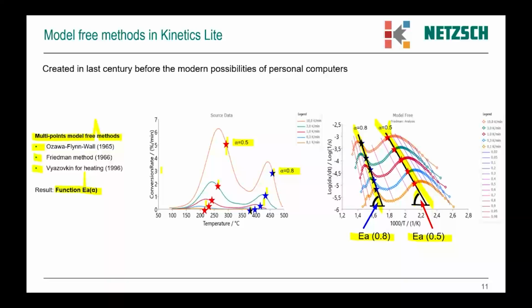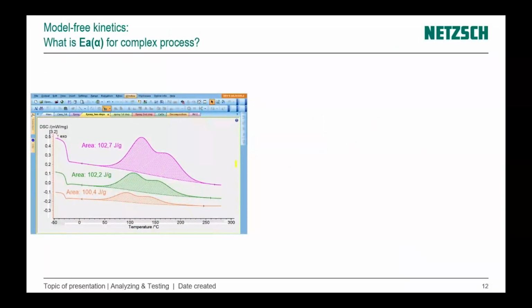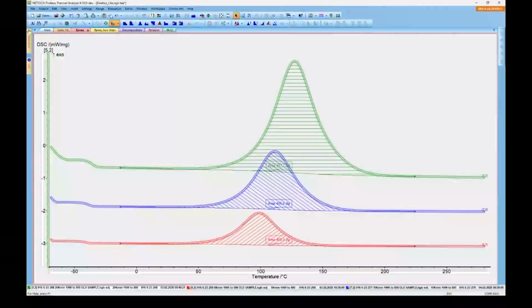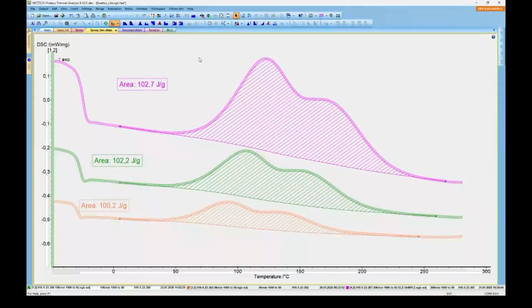This method could be used if the kinetic mechanism is changed during the process. Let's go here. For example, if we have double-step epoxy, here is the beginning of the reaction. We have one step. At the end of the reaction, we have another peak, and here probably is another value of activation energy. And now the question: what is the activation energy for a complex process? How fast could it be calculated? We can go back and just see our data for double-step epoxy curing.